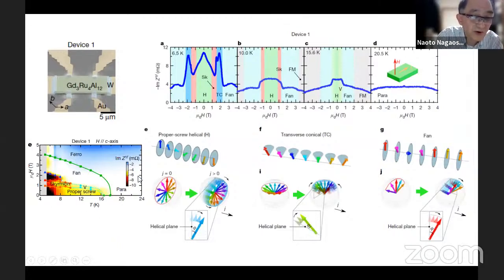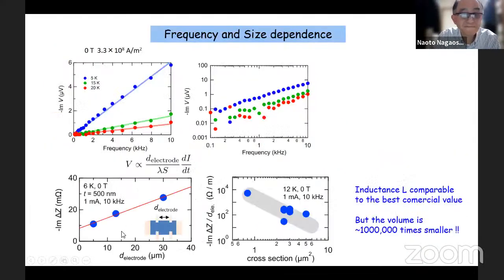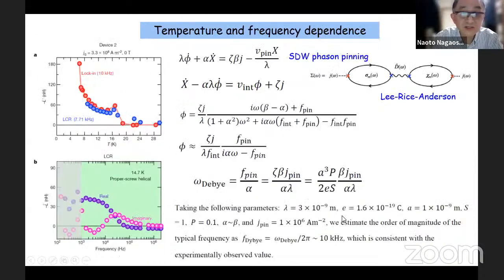So this is a contour map of the imaginary part of impedance, namely the inductance, in the plane of magnetic field and temperature. And it's proportional to omega, which means given by the time derivative of a current. And importantly, this is inversely proportional to the cross section. So this inductance value is comparable to the best commercial value, actually. But the volume of the sample is almost a million times smaller. So then we believe this could be very useful for the miniaturization of the inductor in electronics.